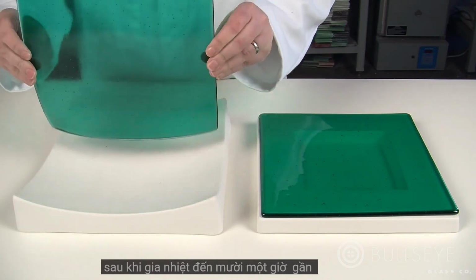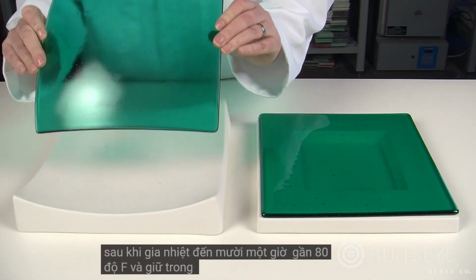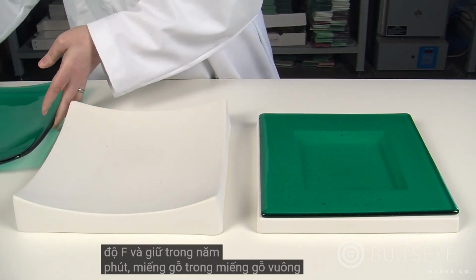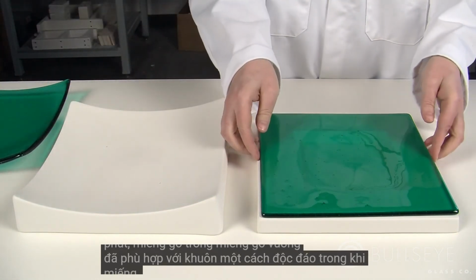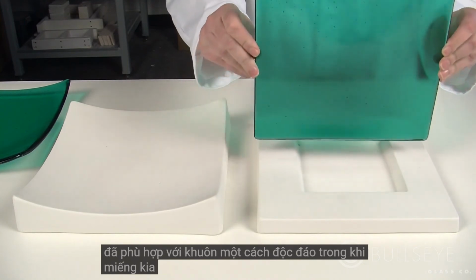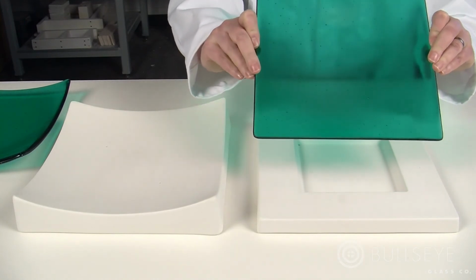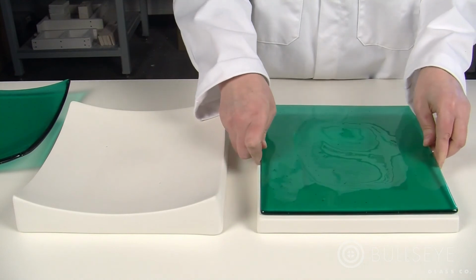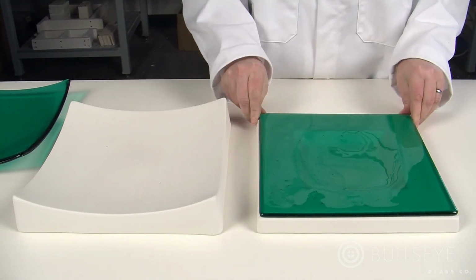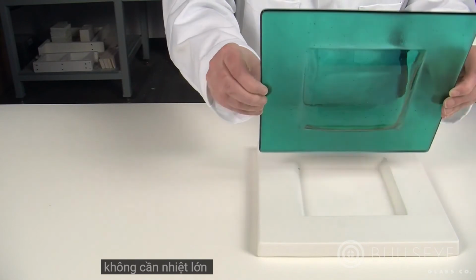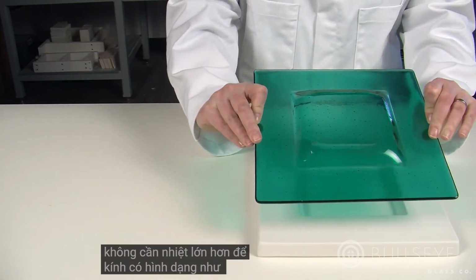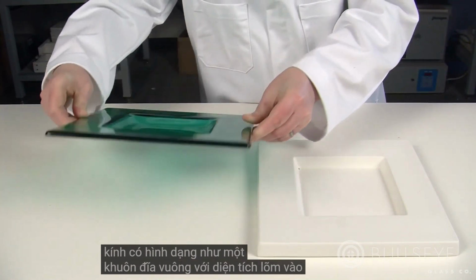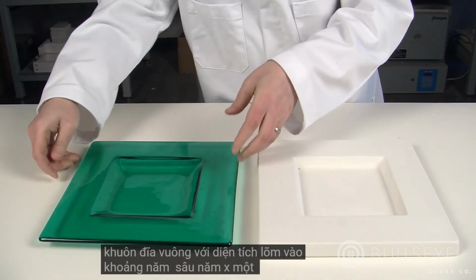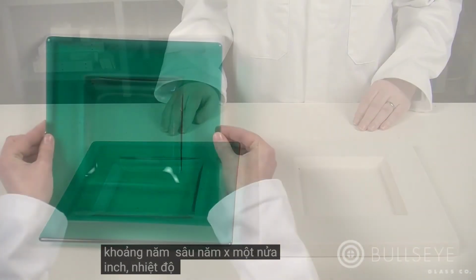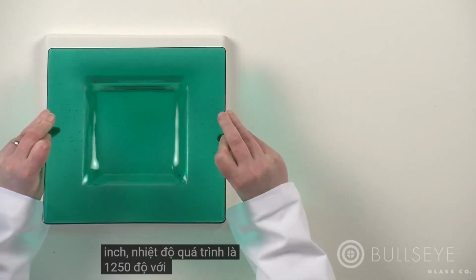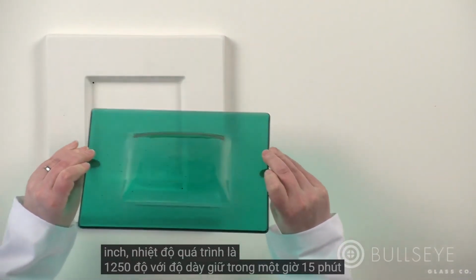After heating to 1180 degrees Fahrenheit and holding for 5 minutes, the piece in the square slumper has conformed to the mold nicely, while the other piece has not. Greater heat work was required for the glass to take the shape of a square platter mold with a recessed area approximately 5 by 5 by 1 inch deep. The process temperature was 1250 degrees with an hour and 15-minute hold.